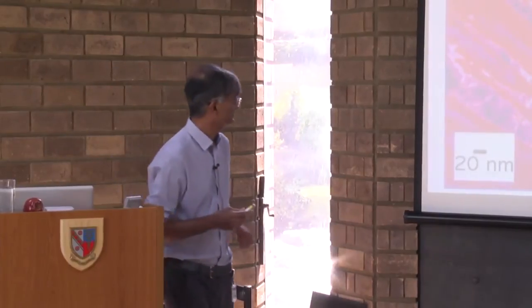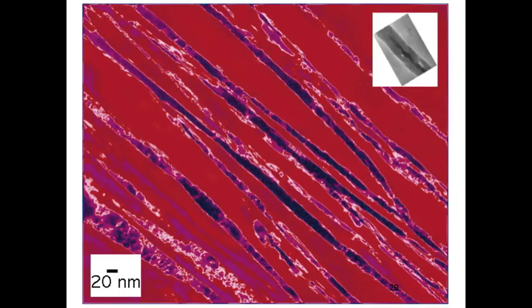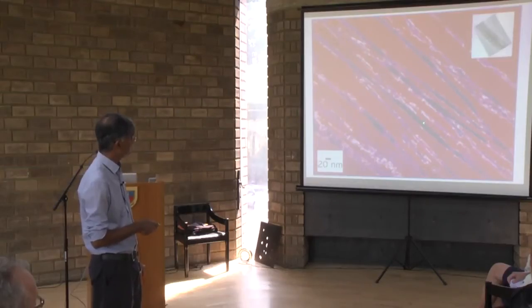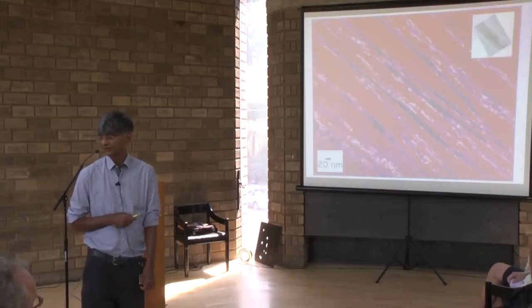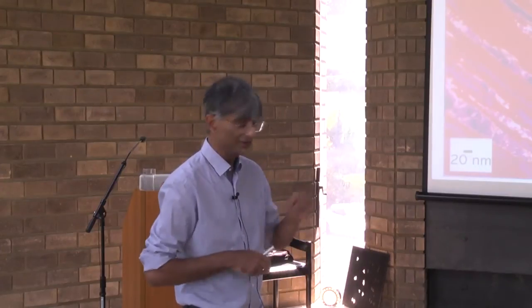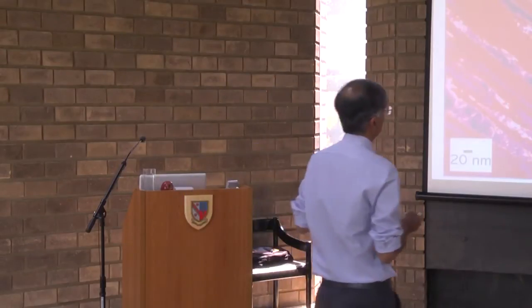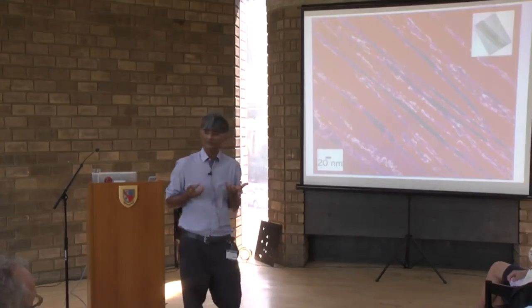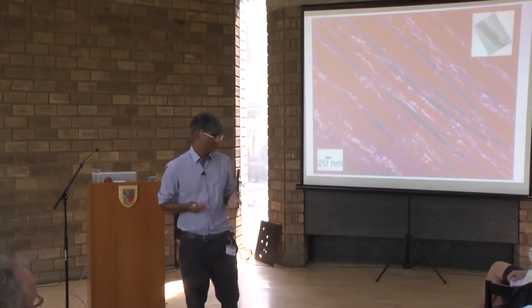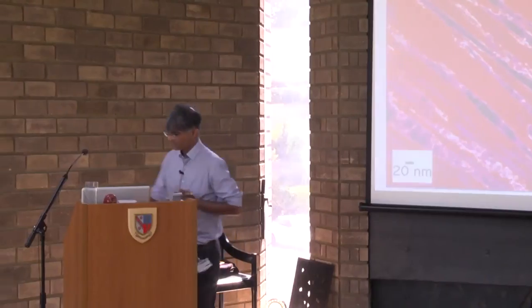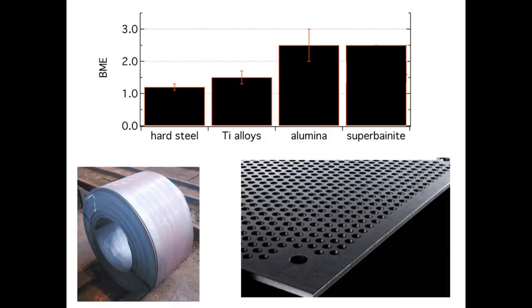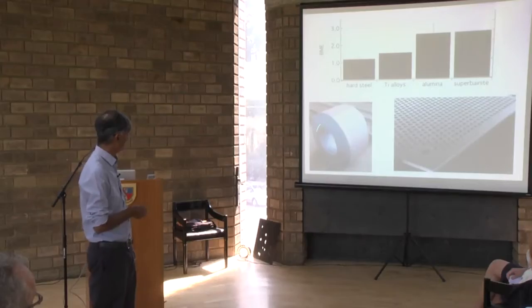This is what we obtained. This is in a transmission electron microscope. The colors are, of course, false. You have parent phase, and these are actually finer than carbon nanotubes. Okay? So by transforming at this low temperature and maintaining all the other properties, we produced crystals inside solid steel which are finer than carbon nanotubes. And there is no limit to the dimensions of the material because this is just a heat treatment. It is now mass produced.